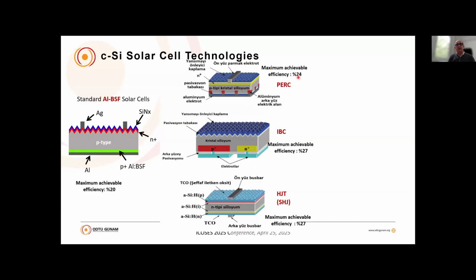The industrial production is still going on, but the average efficiency is around 23%. But it seems that PERC technology is disappearing quickly after the success of TOPCon type of solar cells. Of course, IBC, interdigitated back contact solar cells, is a very promising approach in which the PN junctions are formed on the backside, and the front side has no metal grid, which reduces the reflection from the front surface, which gives us a higher efficiency.